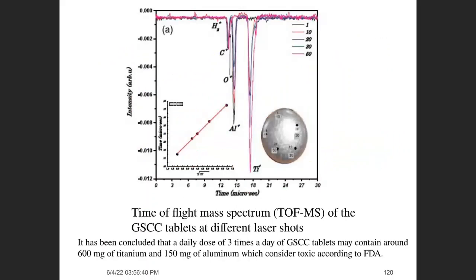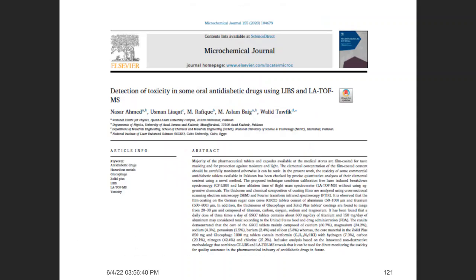The problem is the titanium and aluminum concentrations are more than the allowed dose for drugs. They are very toxic. The dose available in these tablets is three times the daily dose of aluminum and titanium, which represents a toxicity according to the FDA. And we published this finding in the Microchemical Journal.